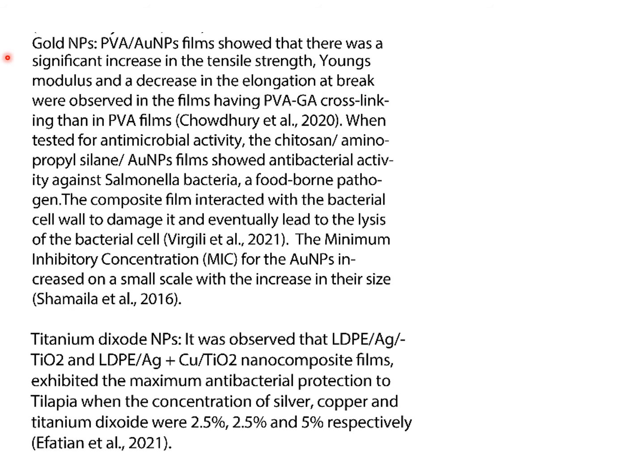Gold nanoparticles showed a significant increase in the tensile strength and Young's modulus. But it was also reported that the elongation at break decreased. When they were tested for antimicrobial activity, gold nanoparticles showed good antimicrobial activity against Salmonella bacteria. Salmonella is a foodborne pathogen. And the minimum inhibitory concentration of the gold nanoparticles increased on a small scale with the increase in their size.